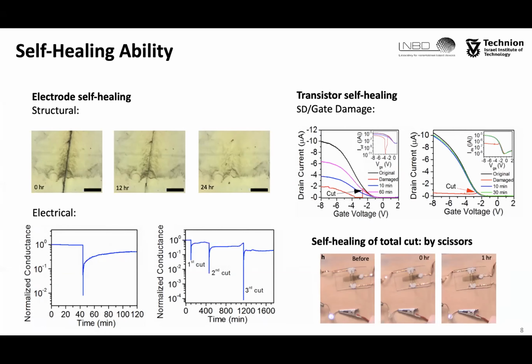In the bottom left figures, you can see a very sharp increase in conductivity at the beginning of the recovery, which decreases with time to reach a plateau. This is probably due to the recovery of the elastic polymer near the damaged area, as well as the surface rearrangement and diffusion of the polymer chains of the PEU.